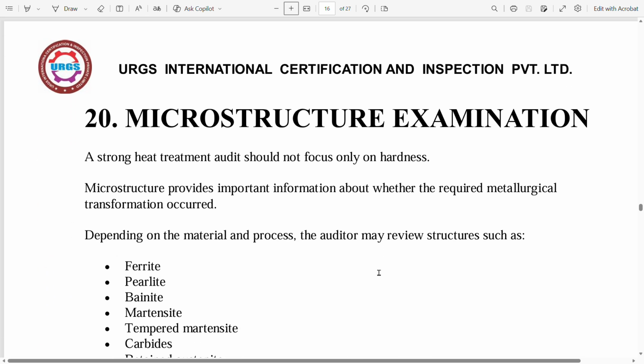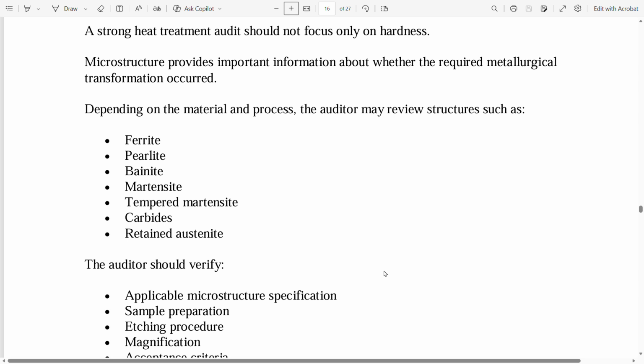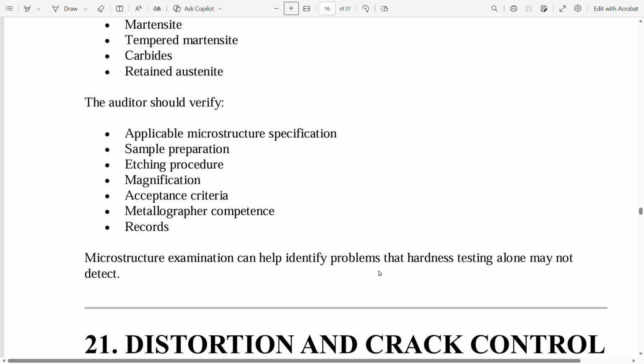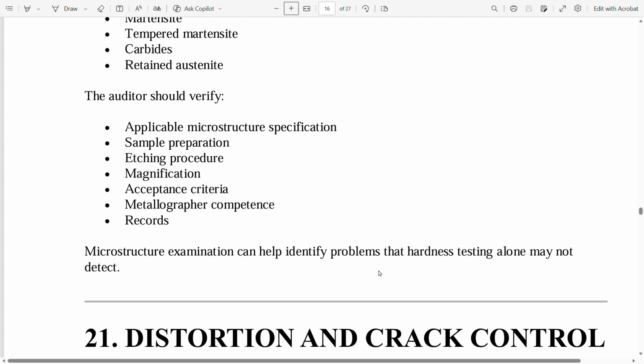The next is microstructure examination. A strong heat treatment audit should not focus only on hardness. Microstructure provides important information about whether the required metallurgical transformation occurred. Depending on the material and process, the auditor may review structures such as ferrite, pearlite, bainite, martensite, tempered martensite, carbides, retained austenite. The auditor should verify applicable microstructure specification, sample preparation, etching procedure, magnification, acceptance criteria, metallographer competence, records. Microstructure examination can help identify problems that hardness testing alone may not detect.